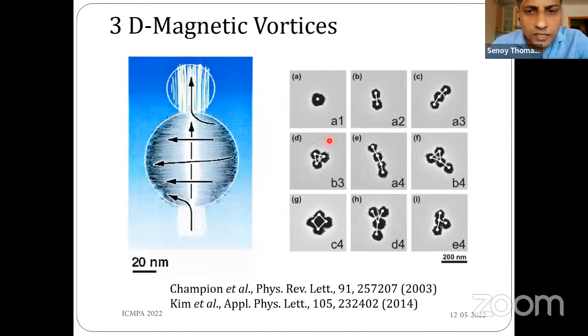So we are also interested in investigating the 3D magnetic vortex spin configurations in spherical nanoparticles. This is very important as far as the self-assembly of these ferromagnetic nanospheres is concerned. Depending upon the available entities, one could result in a chain-like morphology, or a triangular shape, or a Y type, or a square shape. So basically the assembly is driven by the stray field associated with these 3D magnetic spin configurations in these spherical